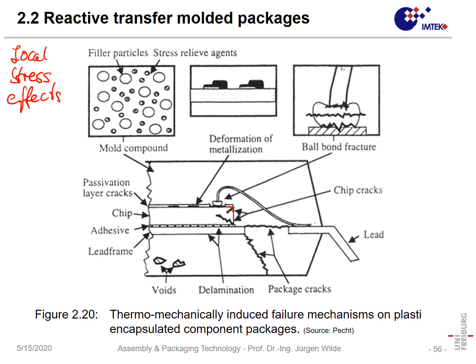So you could say avoiding the sharpest edges by proper processing, by proper sawing of the silicon, by proper cutting down of the lead frames, then you could already avoid such sharp edges, and you could avoid crack formation in the package and in the chip here.